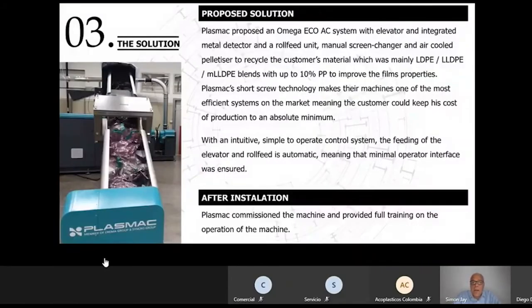For this customer, we supplied them an Omega Eco AC system with an elevator, an integrated metal detector, plus a roll feed unit. It had a manual screen changer and an air-cooled pelletizer. The customer mainly ran low density, linear low density with some metallocene blends, but they also added up to 10% polypropylene to improve the film properties. Again, we commissioned the line, fully trained the customer on the operation of the machine.